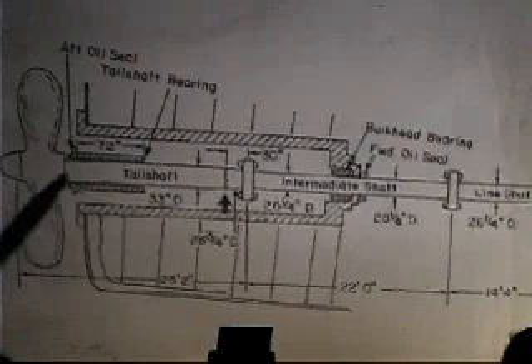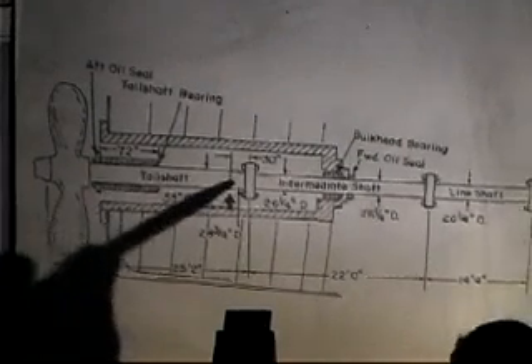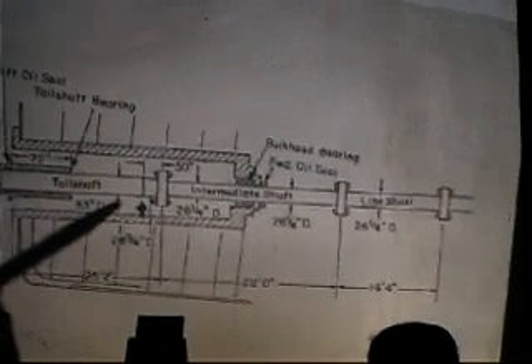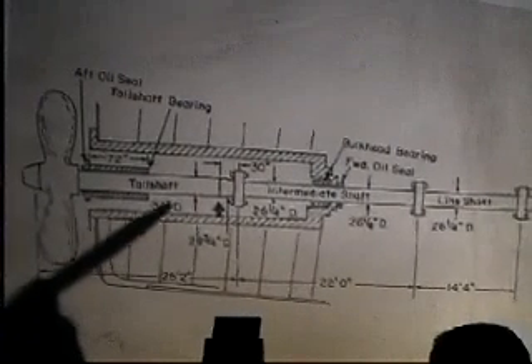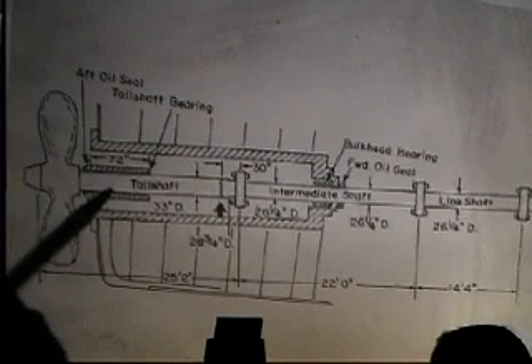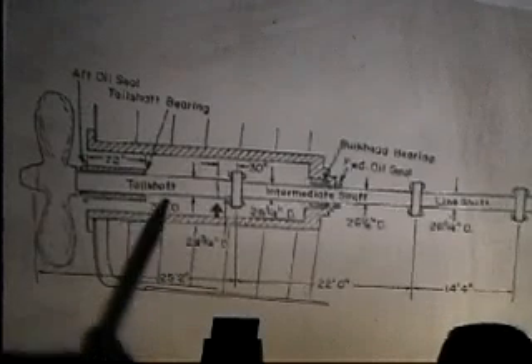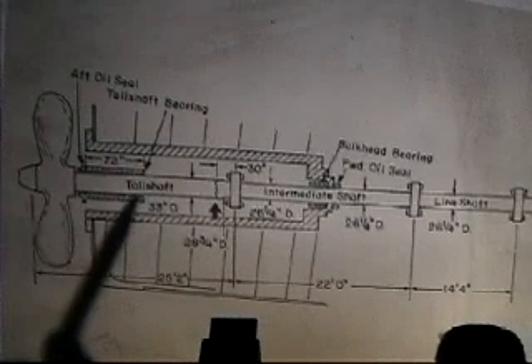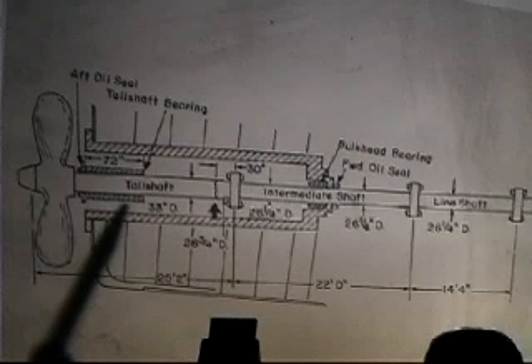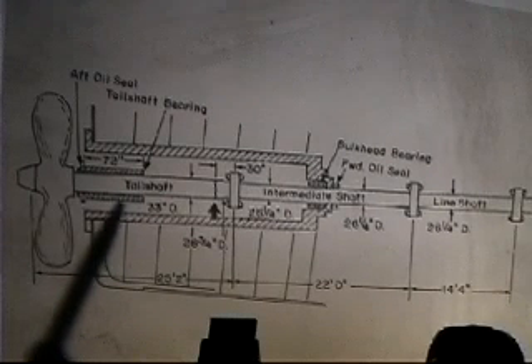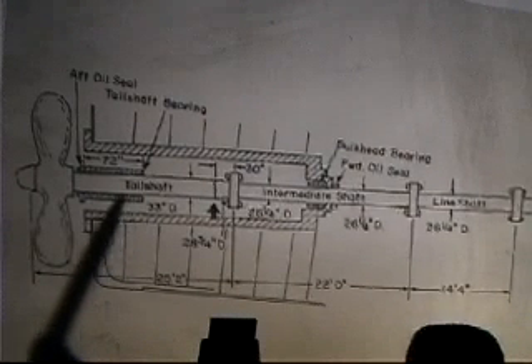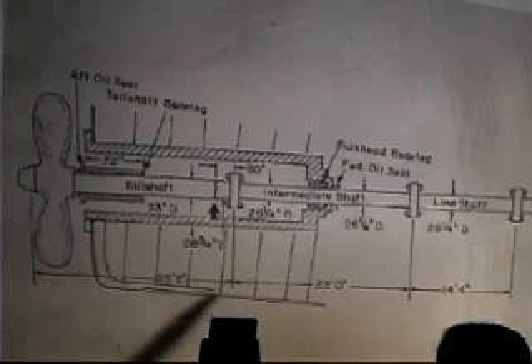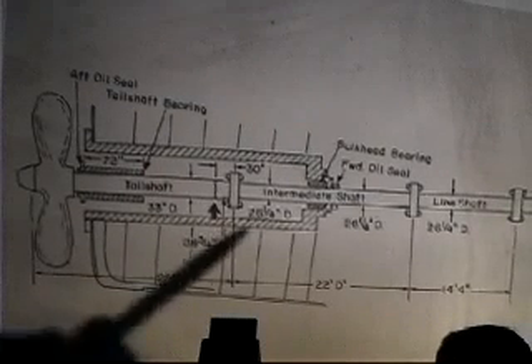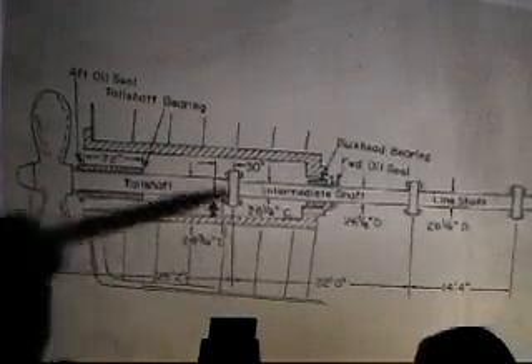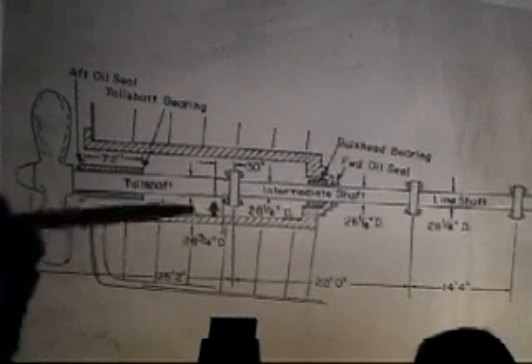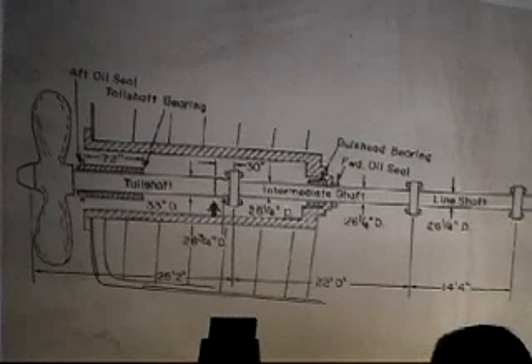This was forged from about a 20-ton ingot. It turns out it was forged at a steel mill in the northwestern part of the United States, and then it was shipped to Quincy. They had to use their largest ingot mold to make this. In fact, this was just at the limit, or maybe even just beyond the limit of their capacity to produce a part this size. But they wanted the business. They also forged the intermediate shafts, which were only 30 inches in diameter. The tail shaft was 33, and that's where it fractured, and that's why they lost power.